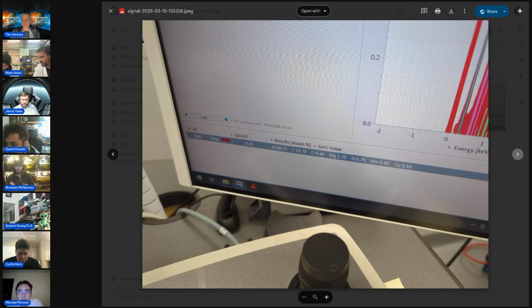So these were the amounts that it measured for each of the elements, assuming we didn't get rid of the carbon and oxygen, which kind of throws things off. And also, it was integrating these. It doesn't add to 100 or anything, but it's integrating these counts over a period. We didn't get to integrate very long before something went wrong with the EDS system anyway, so we've got to debug that tomorrow. But yeah, it's mostly aluminum, a little bit of magnesium and silicon, and maybe some manganese and copper.